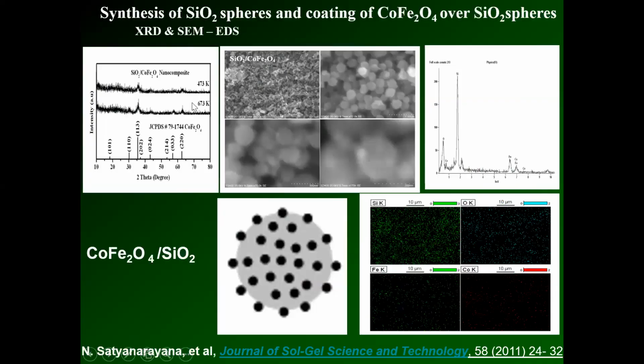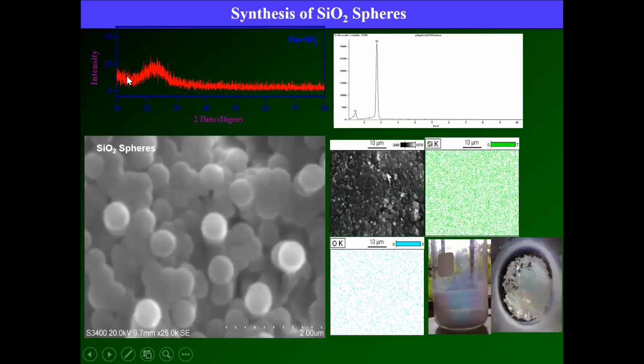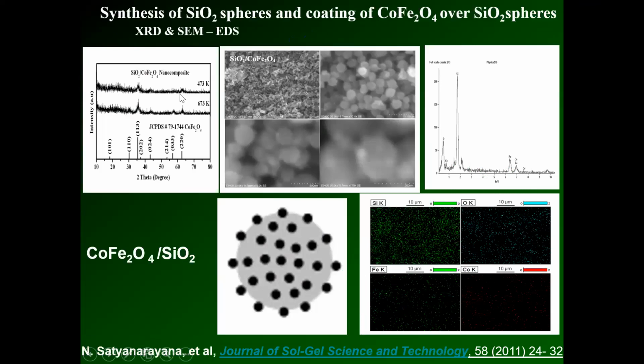So if you take the XRD, you can see the previous one is completely amorphous. Now the next one, you can see there are peaks. When you analyze the peaks, they are crystalline peaks due to cobalt ferrite. So cobalt ferrite nanoparticles exist in SiO2, and of which form we will try to see.